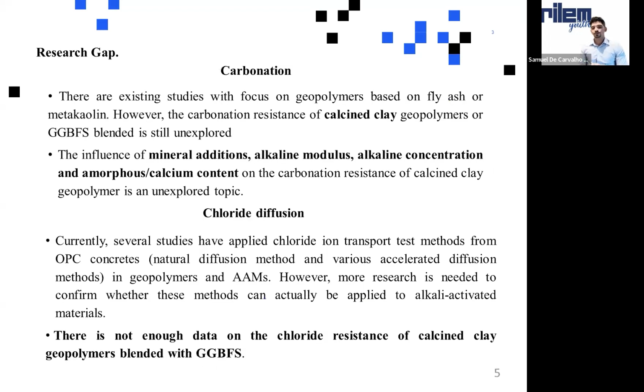The research gap of this specific research inside my thesis was to assess the carbonation resistance of this composite of calcined clay with GGBFS. There are existing studies focused on geopolymer based on fly ash, especially fly ash and metakaolin. However, the carbonation resistance of calcined clay geopolymer or GGBFS blended is still a topic to explore. The influence of alkaline moduli and alkaline concentration, amorphous and calcium content on the carbonation resistance of the calcined clay is still a topic to be explored.